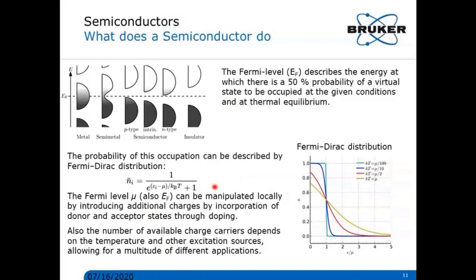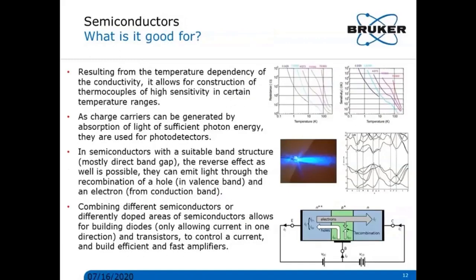And if we cool it down to zero and have an undoped semiconductor, we would find that there's almost no conductivity left. This Fermi level can also be shifted not only by incorporating those so-called donors and acceptors, but by external fields. So in certain geometries, we can now control current through a device, and those properties altogether make the semiconductor materials very interesting for building amplifiers, rectifiers, and potentially light emitters and detectors. And so on the next slide, I will show you a few possibilities of what we can do with it and what has typically been done.